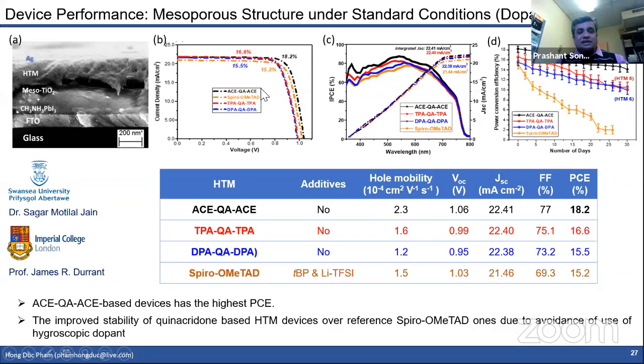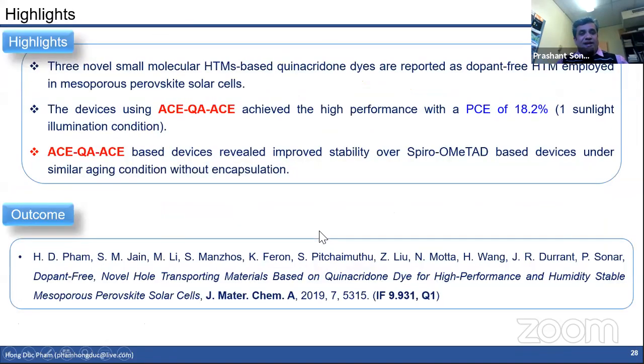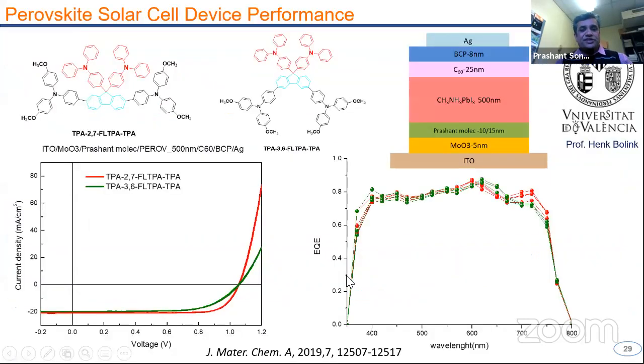These are the IPCE data as well as JV curves, and we can really get a very high short circuit current, close to maybe 22.0. That is one of the highest. But in another device, where we got an open circuit voltage of 1.06, we got a really high efficiency of 18.2. And again, these are the dopant free 3 HTMs, and we published that in the Journal of Materials Chemistry.